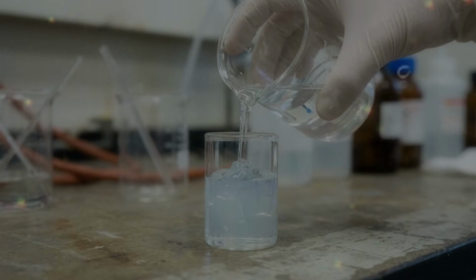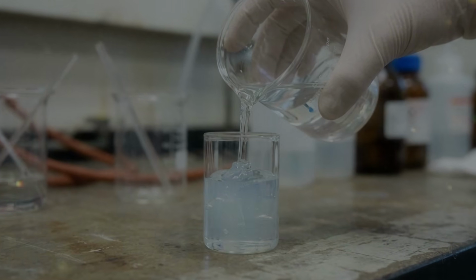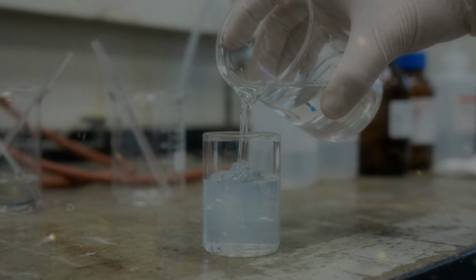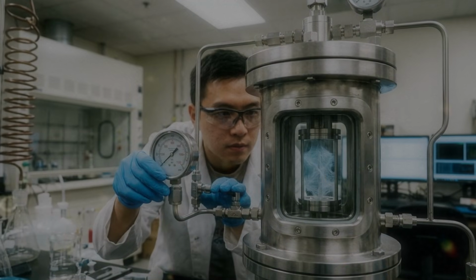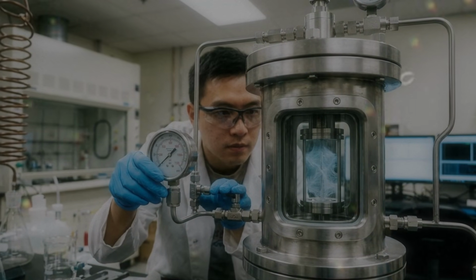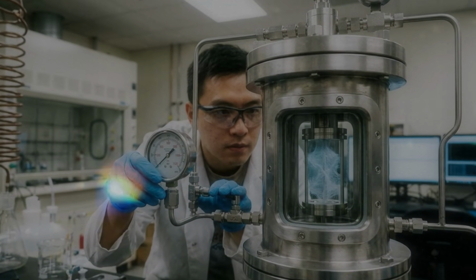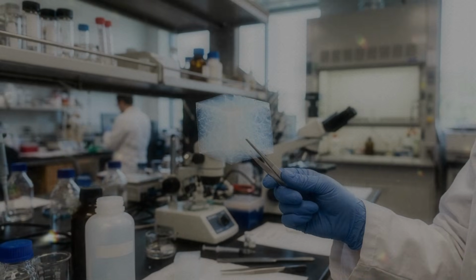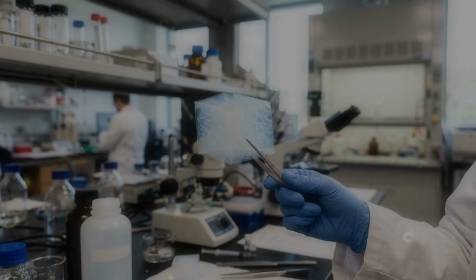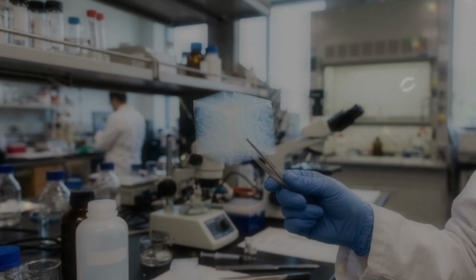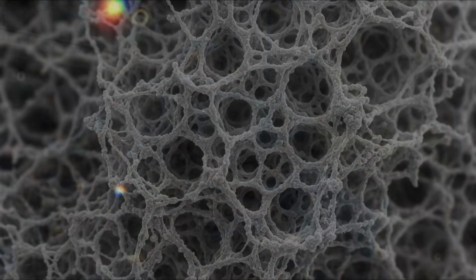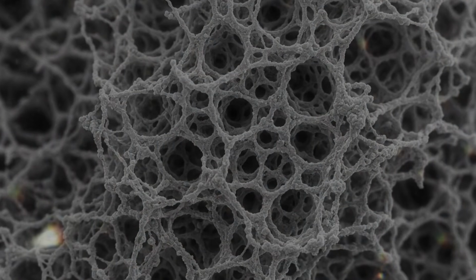Silica aerogel is especially effective as a thermal insulator because silica itself carries heat poorly compared with metals, and the porous structure reduces heat flow even further. A thin layer can provide insulation that would require a much thicker layer of some conventional materials. This does not mean every aerogel is equally good at stopping heat.